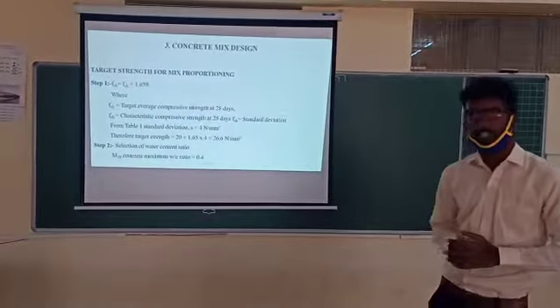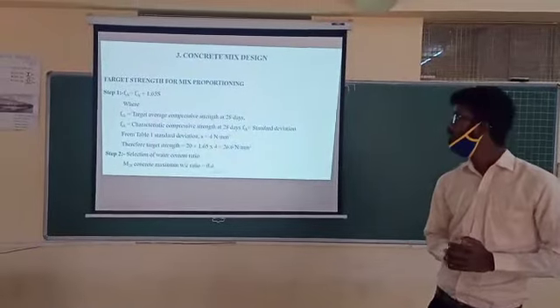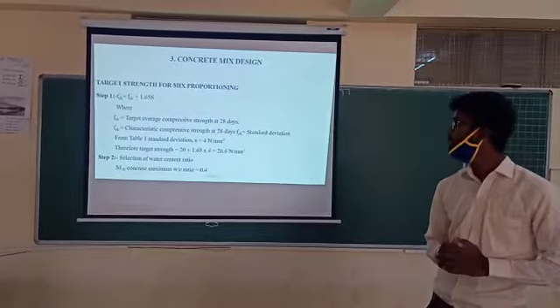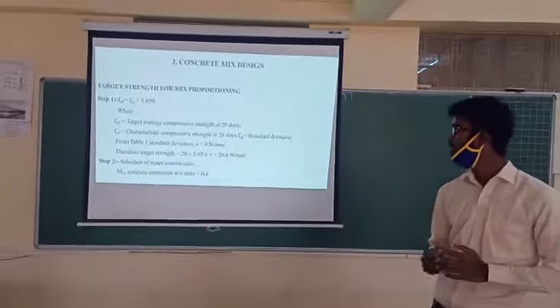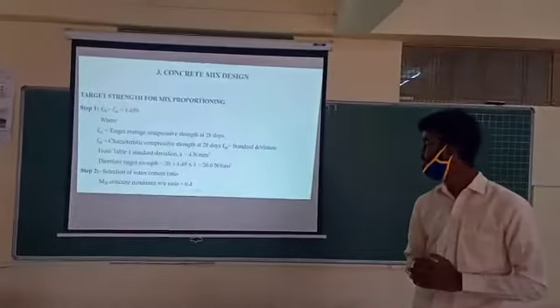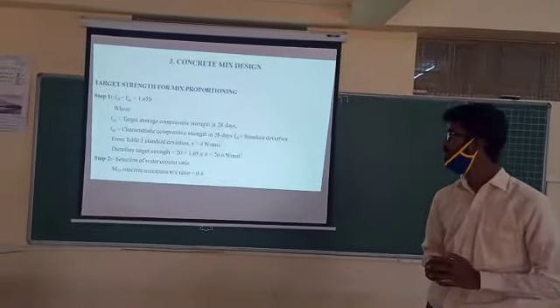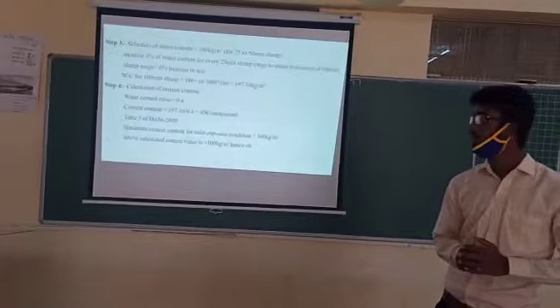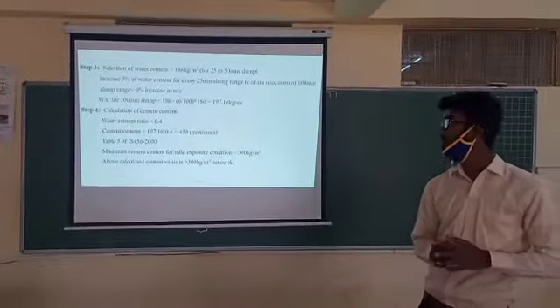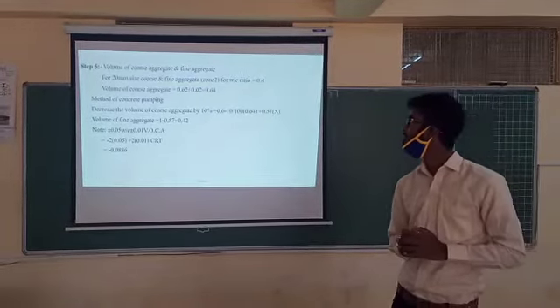And from IS 10262, we got the target strength for the mix proportion. Our target strength is 26.6 Newton per mm square. Use 0.4 water cement ratio, and maximum cement content of 450 kg per meter cube. And the volume of coarse aggregate is 0.64 and volume of fine aggregate is 0.4.